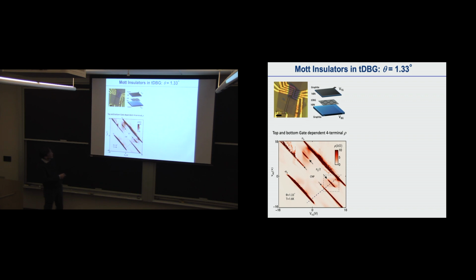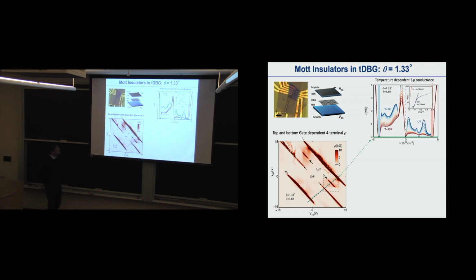So there's certainly a correlated insulating state appearing in the half-filled band, but it only appears with some finite displacement field. This actually matches well with the picture we initially started with. Indeed, if we measure the correlated insulating state as we increase the temperature, it disappears, and we can get the activation energy. Something like a few millielectronvolts—this decent size gap appears and is stabilized by the displacement field.